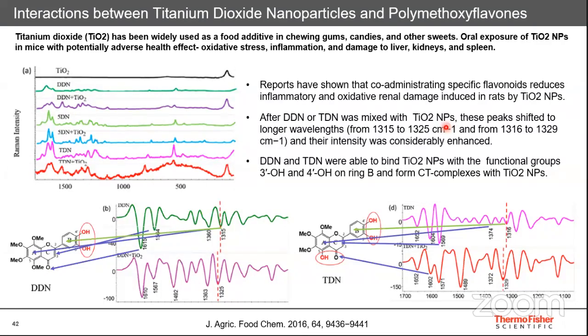So basically what happens is, when TiO2 is in nanomaterial form, the surface of that nanomaterial is exposed. And as you know, when you have nanoparticles, there are always these valence bands, or vacant, unfilled states. The upper layer has the unfilled electronic states of the upper layer molecules, and these molecules interact with other organic molecules and try to get good coordination. This is what they were trying to study.